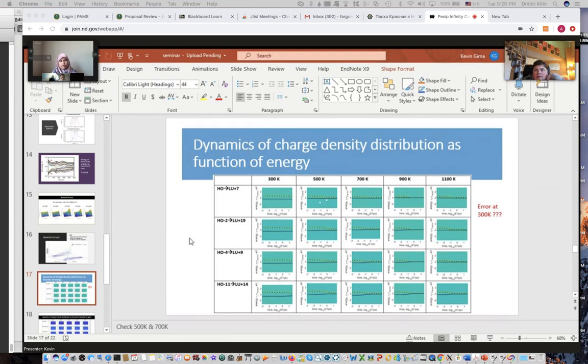Okay. So in these results, I'm studying how my charge density changes with energy. Here at the 300 Kelvin temperatures, you see that there's hardly a change anywhere. But then at 500 Kelvin, 700, and higher temperatures, you see that relaxation occurs, and then essentially the higher the temperature, the quicker the relaxation goes. If you just take a quick qualitative examination of these graphs, that's essentially what happens. So just wanted to quickly point that out.